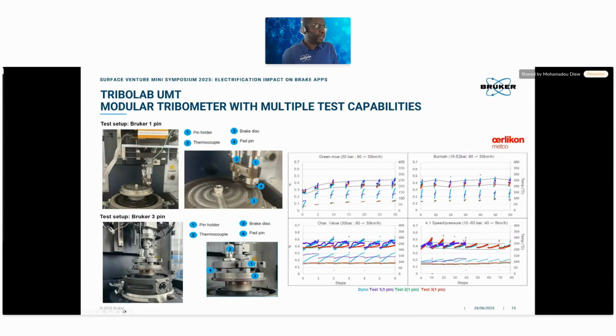In terms of temperature, the energy dissipation through the area is similar. But when you increase the number of parts, you increase the surface, so at the end you will see more heating compared to the 1-pin, where the heating will be quite low. For example, the 3-pin test in magenta is closer to the dyno compared to the other two, which are far off due to much less heating because we only have 1-pin. We can only try to bypass this by increasing the braking time, and in this case the test will probably not be the same as what we are trying to compare.